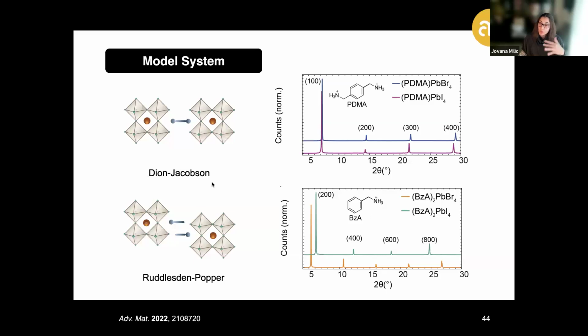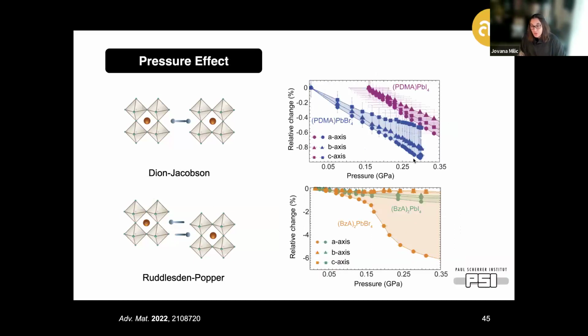Now, when exposing these well-understood layered perovskite architectures to external pressures, we can notice that these structures change across all the lattice parameters that are slightly compressed, especially along the A-axis that particularly corresponds to the spacer layer, and which is most pronounced for this unusual assembly of the benzylammonium lead bromide-based system that was in fact found to be the only system amongst those analyzed that is fully non-centrosymmetric, making it more susceptible to some of these external changes in response to pressure.